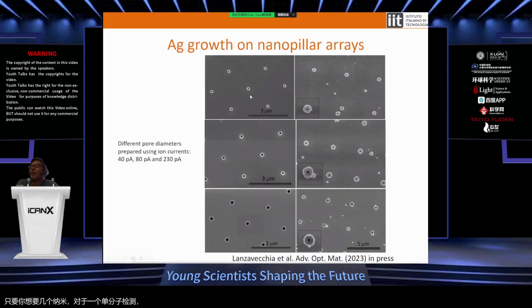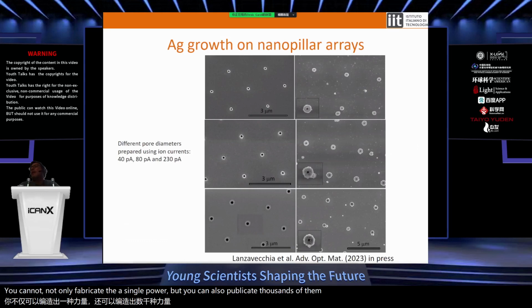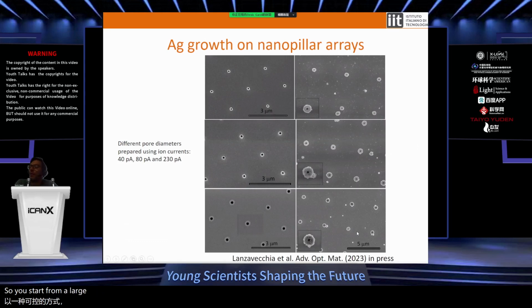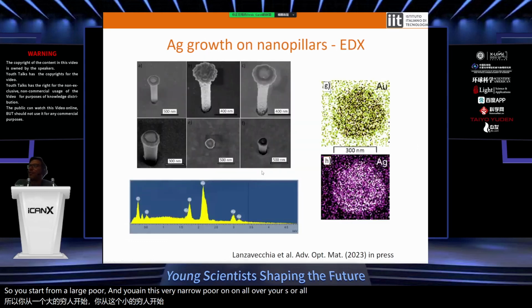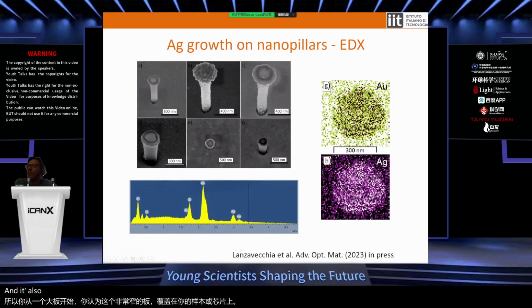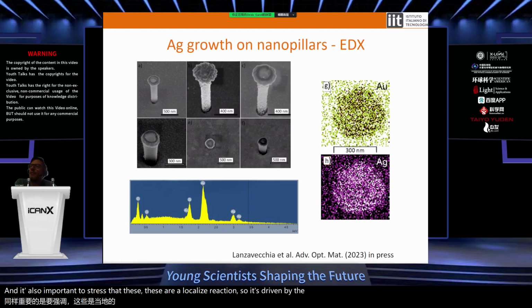This works pretty well also over large array. So it means that you can not only fabricate a single pore, but you can also fabricate thousands of them in a quite controlled way. So you start from a large pore and you attain this very narrow pore all over your sample or all over your chip. And it's also important to stress that this is a localized reaction, so it's driven by the plasmonic field. So you can demonstrate that the deposition happens just over your structures, not all over the sample.